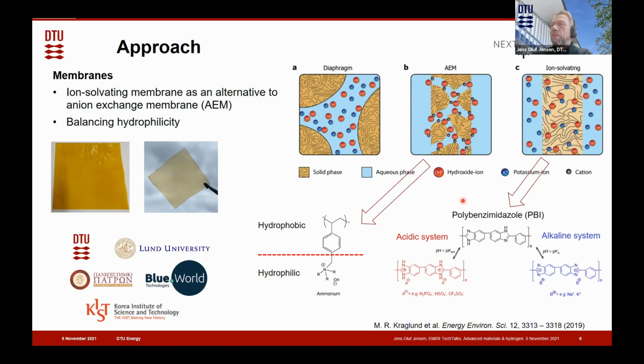We're going to make a membrane by material that can just take up the electrolyte. You get a sort of gel-like structure. That's why it's called ion solvating. So it dissolves the ions and the water from the electrolyte inside. And that's exactly the same system that we've worked with for many, many years, also together with Danish Power Systems, now Blue World Technologies, that we met this morning, with the PBI, the polybenzimidazole polymer that is doped with phosphoric acid, and that is what they do at Blue World for fuel cells. Now we have started going the other way, dope it with potassium hydroxide instead, and then we get an equally good ion conductor, which we can use in the alkaline system.